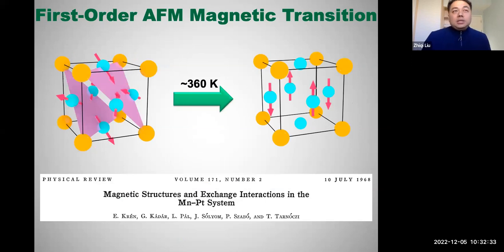Actually, manganese-3 platinum is a very unique material. It's quite similar to iron rhodium. Below 360 K, it has a non-collinear triangular spin structure. It's also antiferromagnetic. But above that, it goes through a first order phase transition into a collinear antiferromagnetic phase.